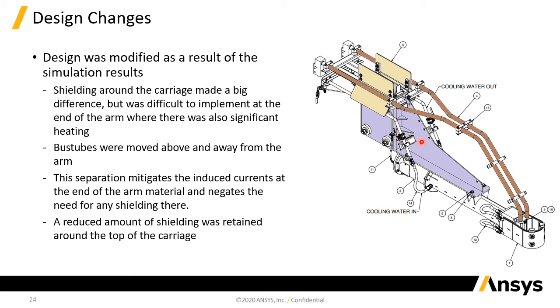On the thermal electric side, the efficacy of the shielding cannot be denied. However, the possibility to implement that along the full length of the sail was limited, so instead we chose to eliminate the problem entirely by raising the bus tubes. It did come with the trade-off of longer bus tubes, which had a marginal cost implication, but it was considered to be worth it. However, proximity to the carriage and the topmost rollers could not be avoided, and as such we are left with a much smaller but still very effective shielding at the top to protect those elements.